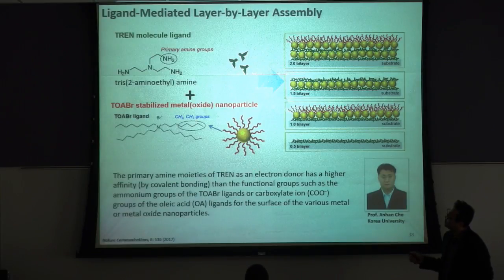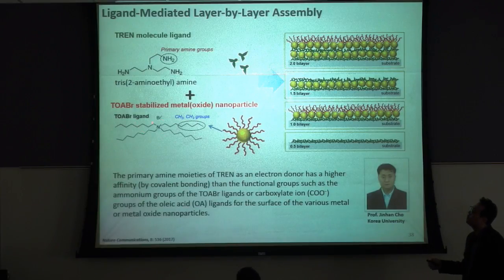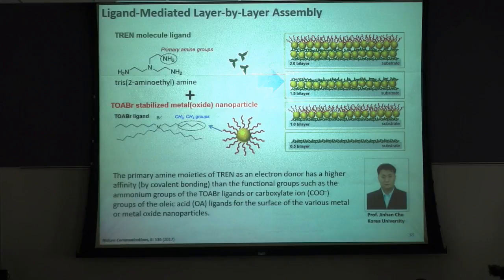So different batches include metal or metal oxide nanoparticles, which are stabilized by this kind of bulky ligand. This ligand is tetraoctyl ammonium bromide. This ammonium group attaches on the surface of the metal oxide nanoparticle and gives some colloidal stability to the nanoparticle. So we first dip the substrate into the TOABr molecule solution. Then TOABr adsorbs on the surface of the substrate.